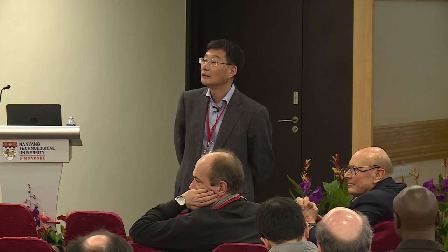I have many questions, but I'll just ask one. Related to the manganese-oxygen stretching frequency that you report, can you explain again why you think that suggests you have a manganese 7? Because it's only... You mean manganese oxide? In the manganese oxide, right? In manganese oxide, yeah. To me, it only suggests that you have a manganese-oxygen multiple bond, but it doesn't have to be manganese 7, right? It could be manganese 5.